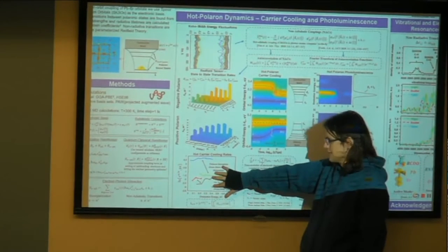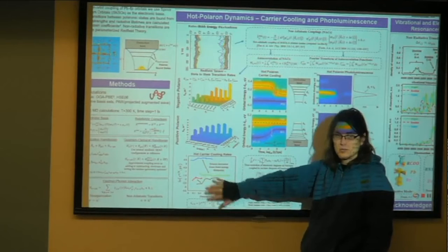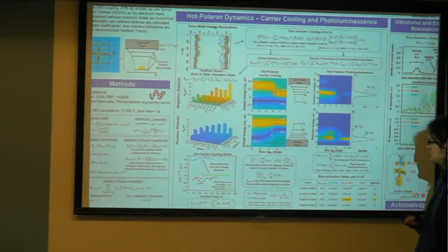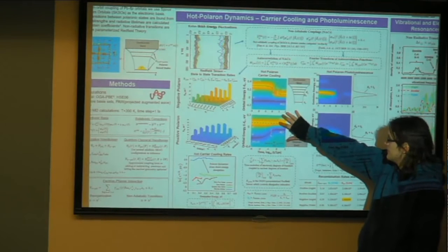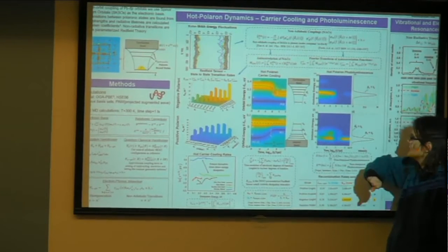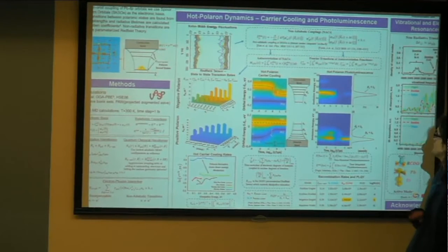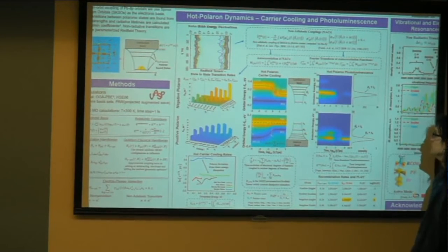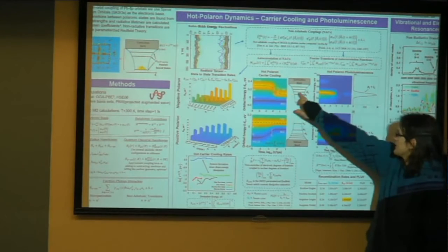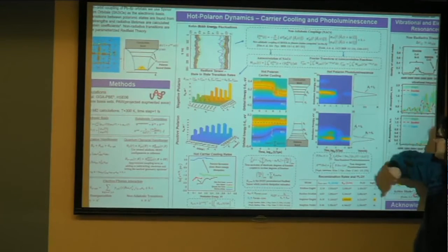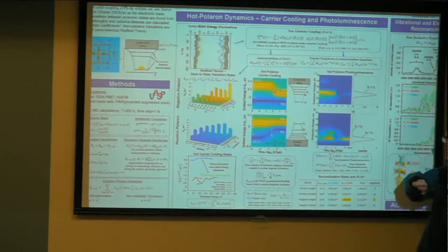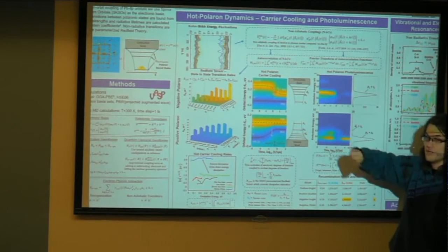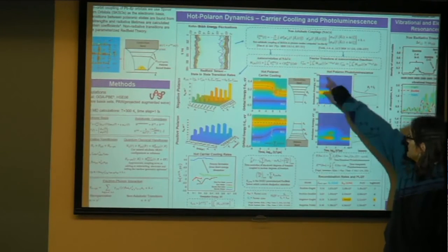So that's just a confirmation that our methodology is working as expected. And so it's the non-radiative relaxation in the excited state. But you can also look at radiative recombinations in the excited state. So along the same trajectory, you can plot the oscillator strength at each time step, and then look at how likely it is to emit a photon. And that's what these plots show.